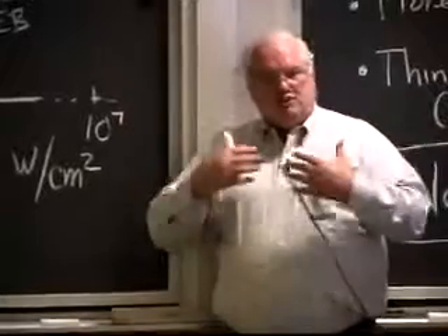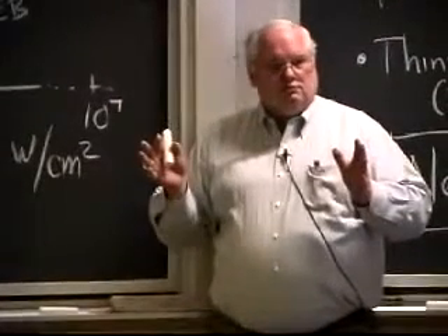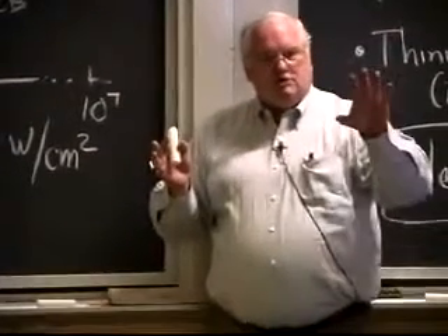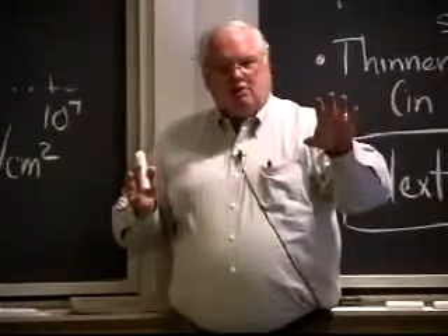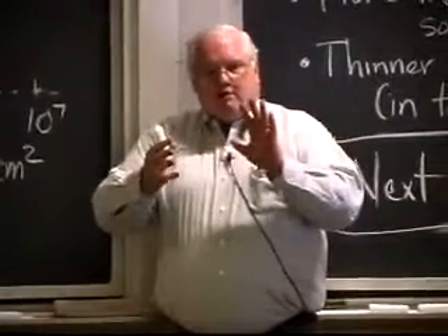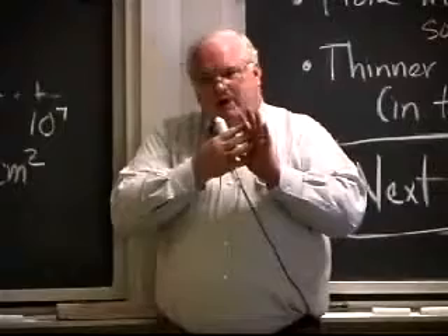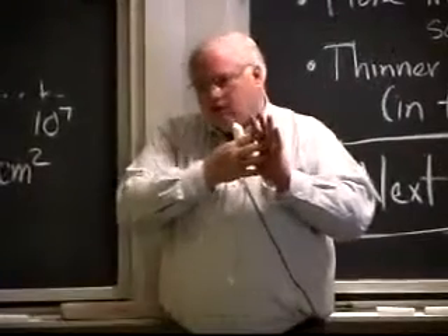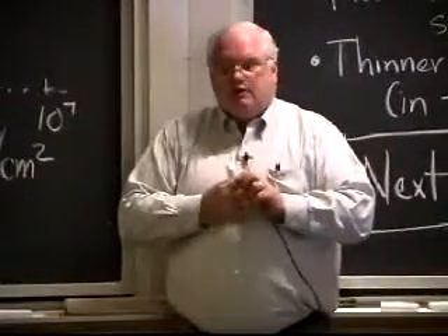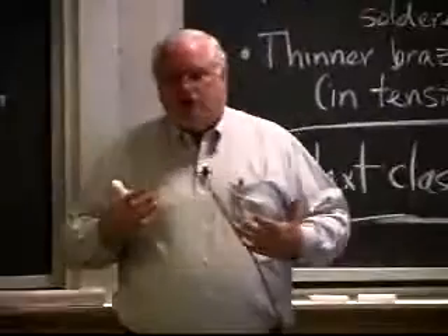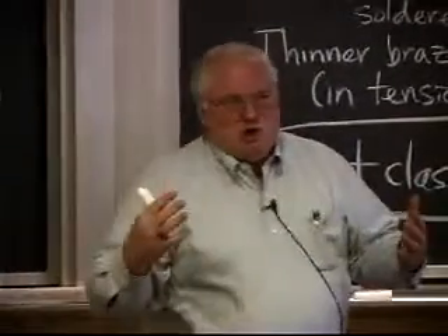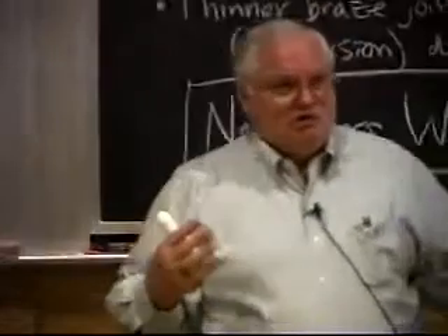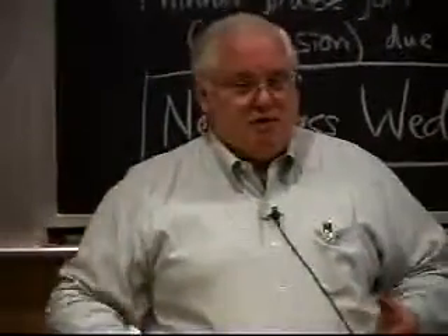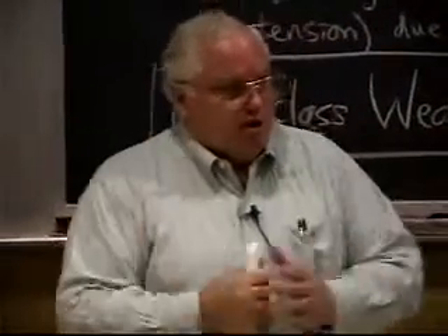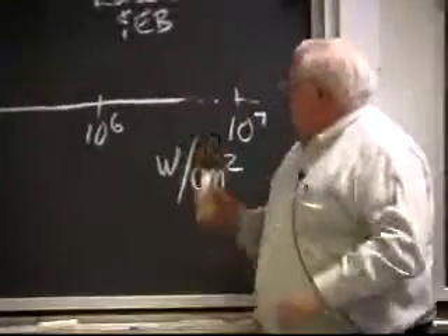You send a shock wave through the material. At 10 to the 8th, you basically start shock hardening the material. You essentially have a little explosion on the surface because you're putting heat in so rapidly, the material wants to expand, but it's got inertia, and the expansion of the heated metal just sends a shock wave through the material. At 10 to the 8th, that shock wave can be 100,000 psi. You could shatter the material. So if you get 10 to the 8th on a laser weapon, the thing will just shatter from the thermally induced stresses of a shock wave on the surface.